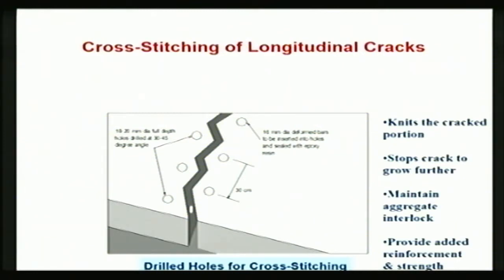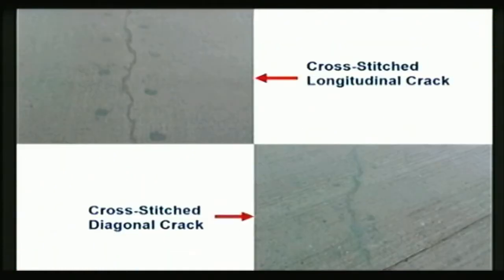In cross stitching we make inclined holes from alternate sides, and then in those drill holes dowels are inserted, and then the annular space is filled with epoxies and mortar. On the top surface we will see only circles like this. We have a longitudinal crack which has been cross stitched. You can see only circles at the surface.